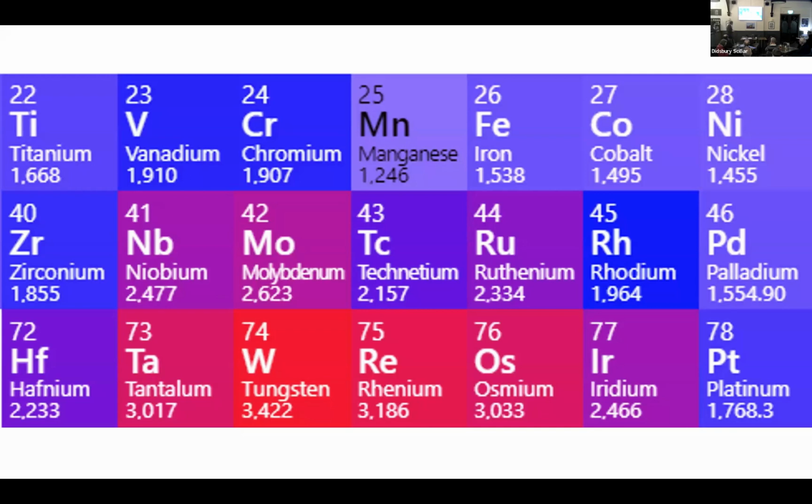There we go. Right. These materials all absorb neutrons, and the neutrons create unstable isotopes, creating a lot of radioactivity. So another problem we have is that we want the isotopes that we do generate to have short half-lives. We want them to decay off, so that we're not producing nuclear waste for the next 1,000,000 years. We want the nuclear waste to decay off within the order of 100 years.